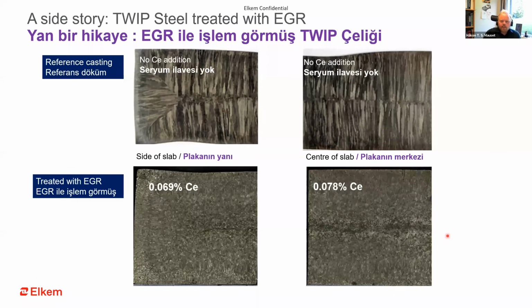So this is a bit of a side story. This is not wear-resistant manganese steel for mining applications. This is TWIP steel, which is typically 20 to 24% manganese, but they are continuously cast and they are advanced high-strength steels. So this is the reference casting from a continuous casting machine. No cerium addition here. And this is the side of the as-cast slab. Here we see a really coarse-grained columnar zone, and we see this typical cross here. And this is the center of the slab. Here you still see really large columnar grains.